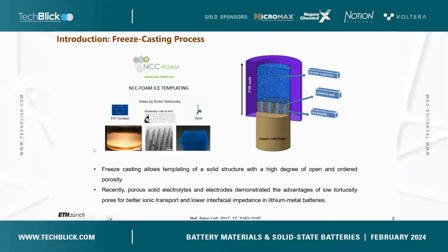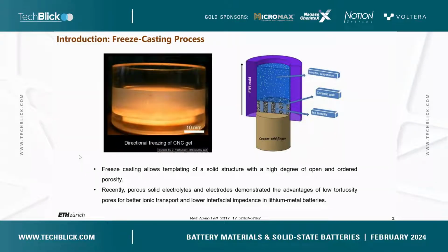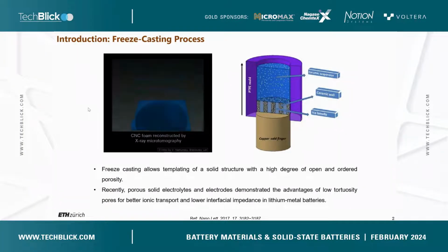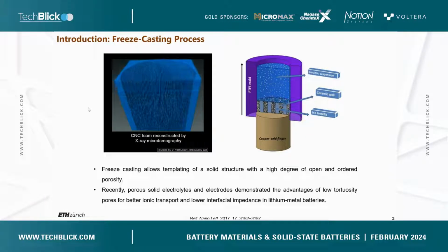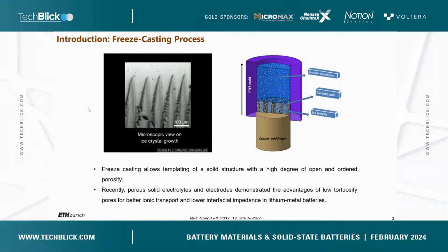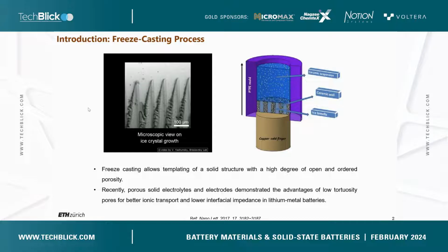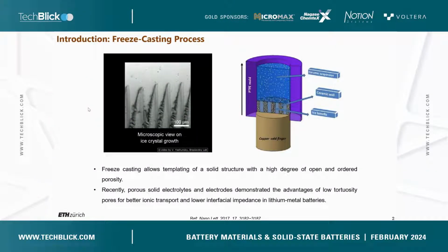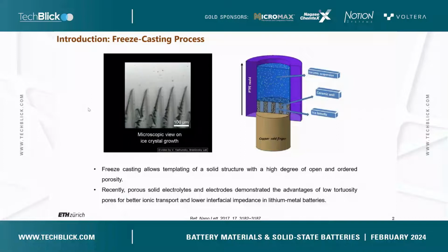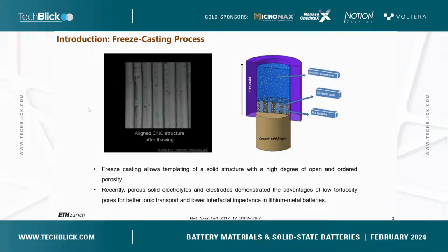This short video here illustrates freeze casting being applied to a cellulose nanocrystal foam. We can clearly see the vertical temperature gradient here. You can see the directional freezing of the gel, which is placed on the mold, and this directional freezing leads to the formation of vertical ice crystals. This is a tomography image of the CNC foam. When these ice crystals grow in this vertical direction, they push the ceramic particles towards the sides. And once the ice is removed, we can generate these porous scaffolds.